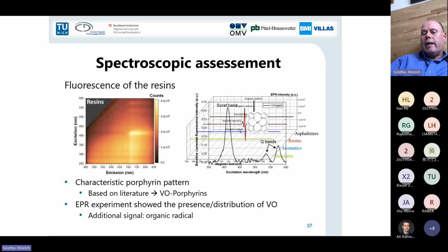And one idea is that this might play an important role also in the aging processes, since this is very prone to absorb light. So then, knowing about the porphyrines from the fluorescence, we had a look at the vanadyl of the vanadium oxide, which is active in the EPR because it has a free electron, the vanadium here. And you see also here the EPR signals, which correlate then with the fluorescence signal and really show us that these complexes exist and that we can learn about the organic radicals, the vanadium oxide, the porphyrines, and how they behave during aging.